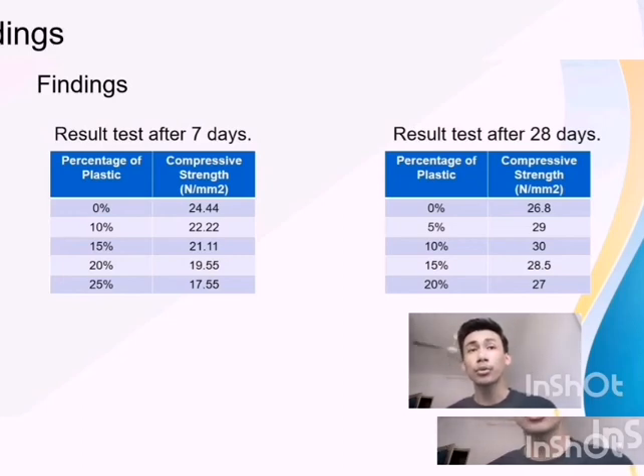So what can I conclude from this finding? At 7 days of the test, natural concrete has the higher compressive strength, and the lowest is at 25% added plastic, which has a compressive strength of 17.55 Newton per millimeter squared.